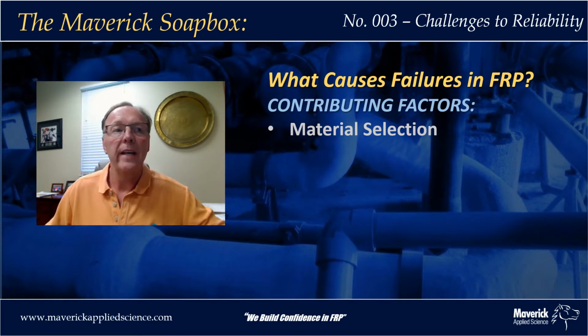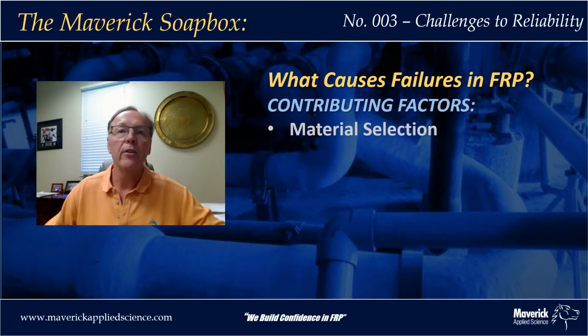Now we're going to drill down on each one a bit, and the first one we're going to talk about is material selection. Examples of material selection deficiencies might be improper resin selection, thermoplastic lining selection in the case of dual laminates, and selection of veil materials. All these would be examples of improper material selection. Of those cases examined, 7% of the time we found improper material selection to be a contributing factor.